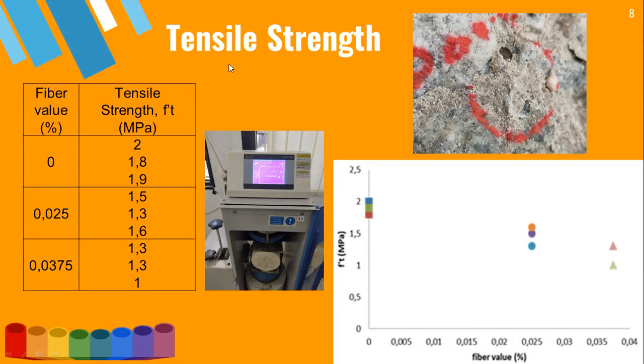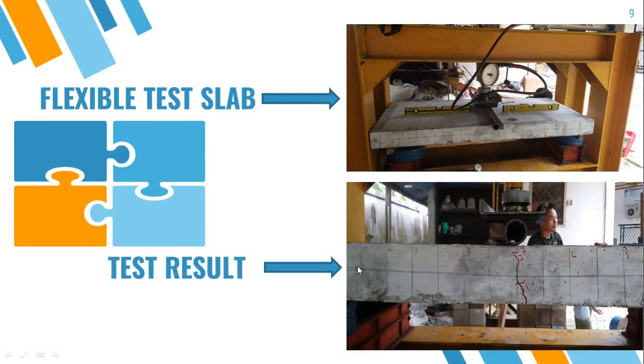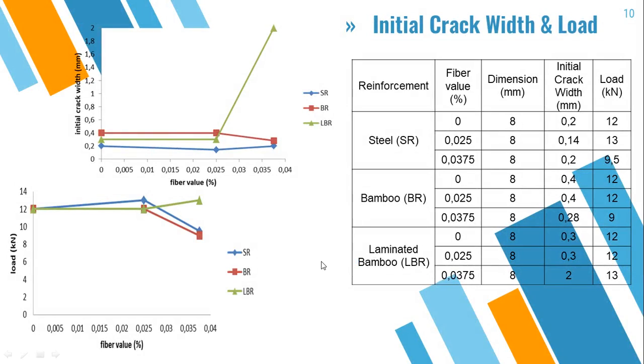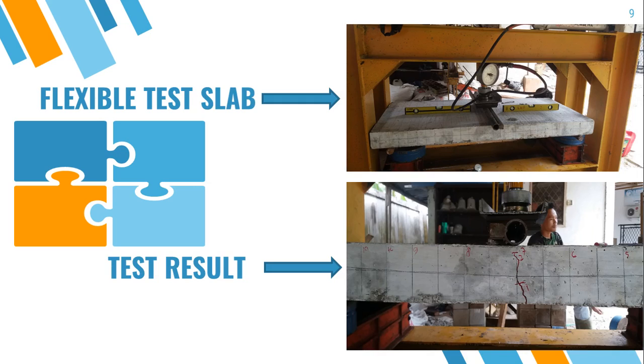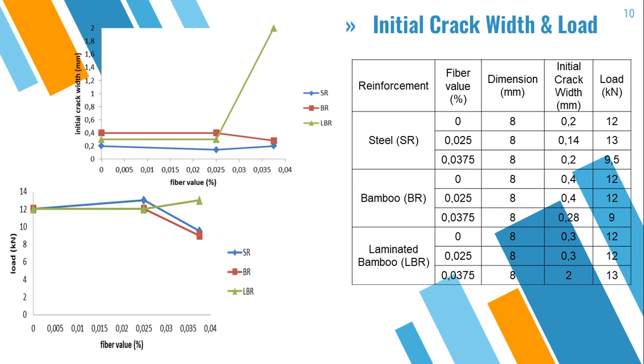For tensile strength, we get a decreased value. After adding the fiber, we get decreased tensile strength, and we can see this in the tensile strength graph. For the flexural test of the slab, we get the initial crack width and loads.